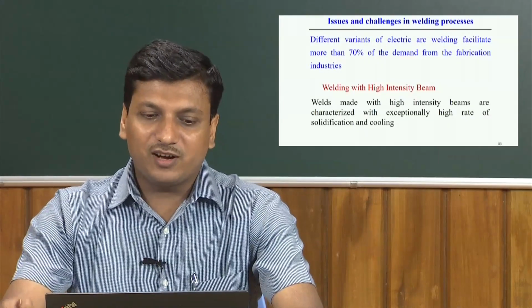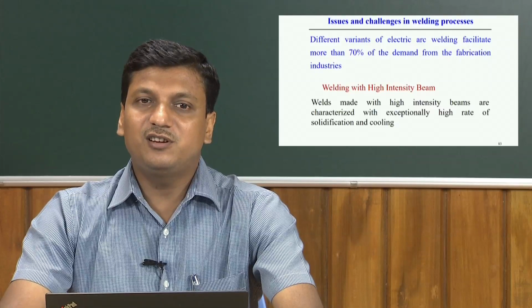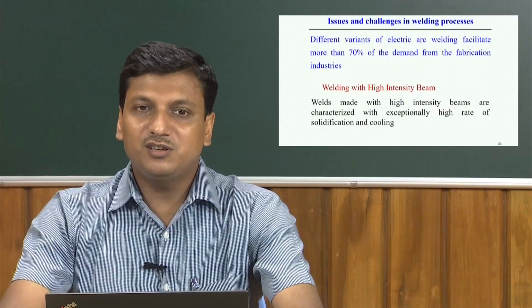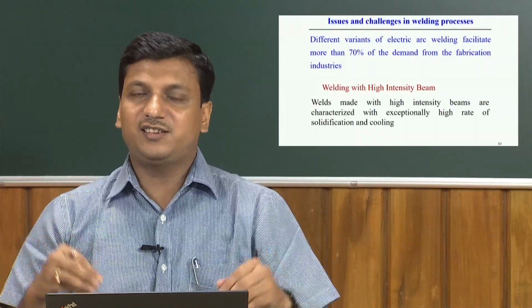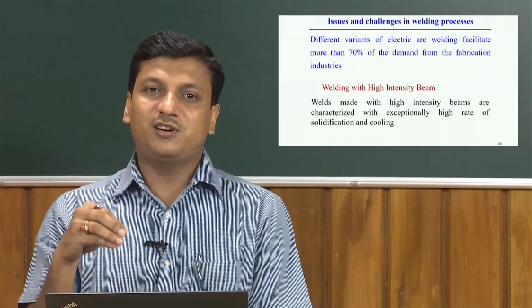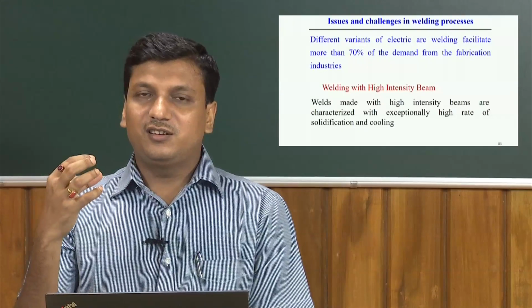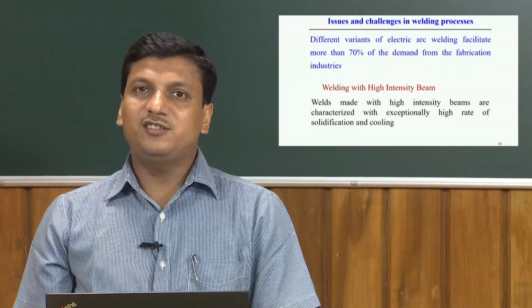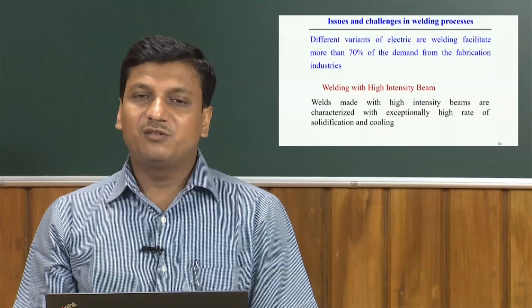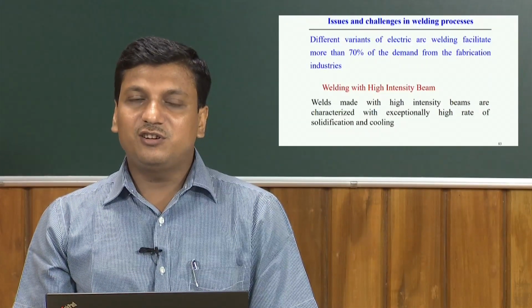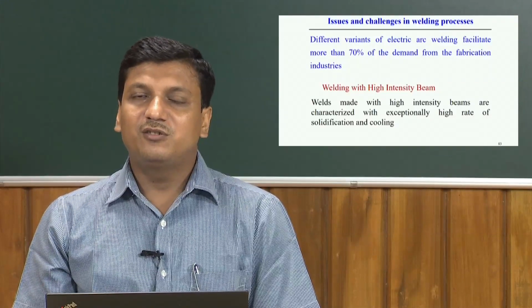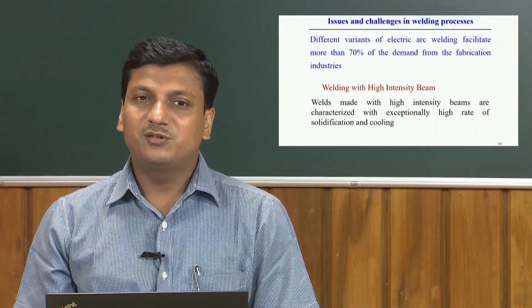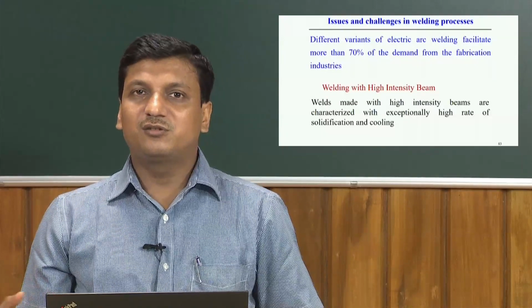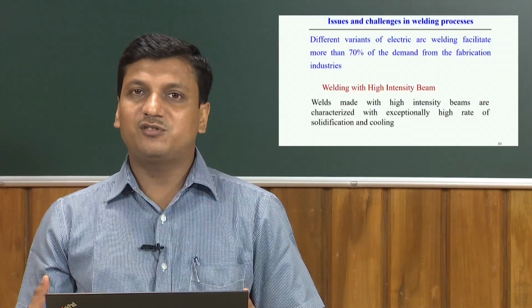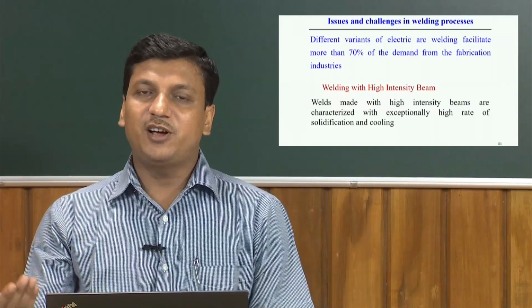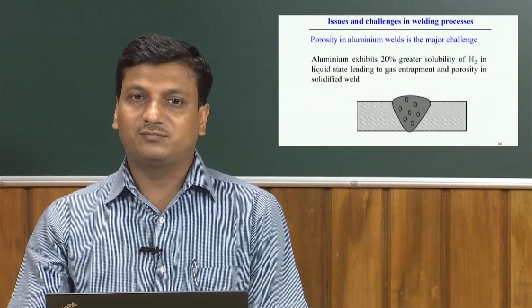But one of the significant aspects of welding with a high intensity beam is the excessively high concentration of heat, while at the same time the rate of cooling is normally very high. So, a high rate of solidification and cooling is normally observed in high beam energy processes. That rate of cooling or solidification impacts the final weld microstructure.